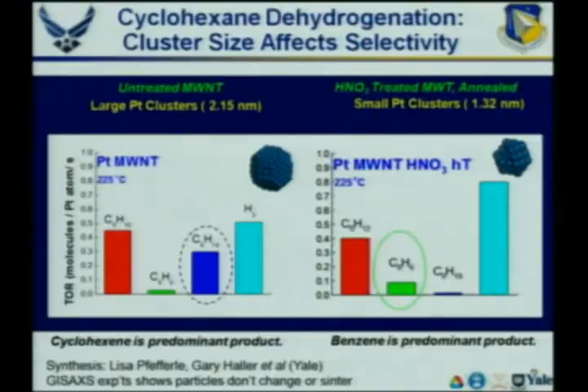And in these experiments, they've looked at dehydrogenation of cyclohexane using different platinum catalysts. These are platinum clusters that are 2.15 nanometers, supported on some multi-wall nanotubes, so supported on a carbon substrate, and then some smaller clusters that are 1.32 nanometers. And you can see there's very different reactivity. With the larger platinum nanoclusters, you see cyclohexene as the major product. So this has lost one molecule of H2 in the process, and a little bit of benzene.